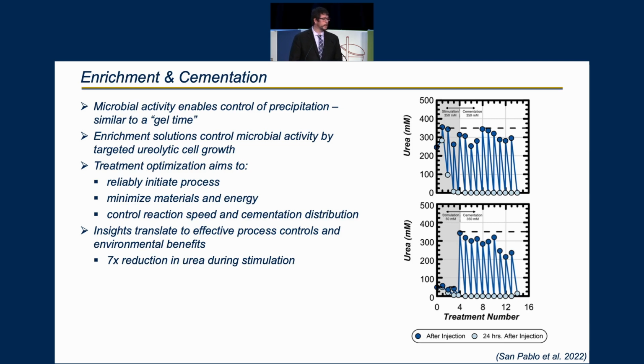For example, the data set shown here is coming from 2 soil column experiments during a typical treatment program. One column received a standard treatment concentration of 350 millimolar urea, while the other column received 7 times less urea. What we see is that upon transitioning to cementation around day 4, we see that there's no real significant differences in activity despite the fact that we were using 7 times less urea. And of course, we were able to significantly reduce those concentrations and material and energy costs associated with that.